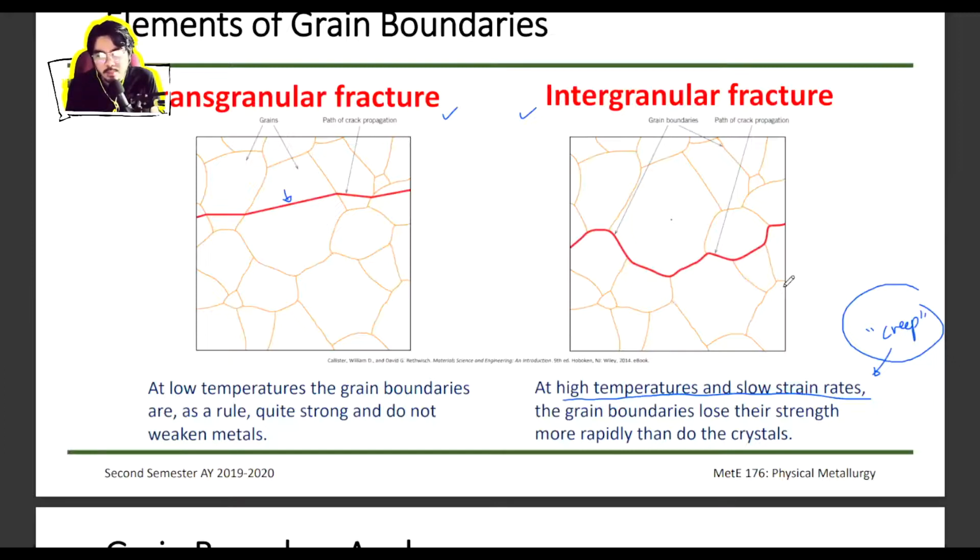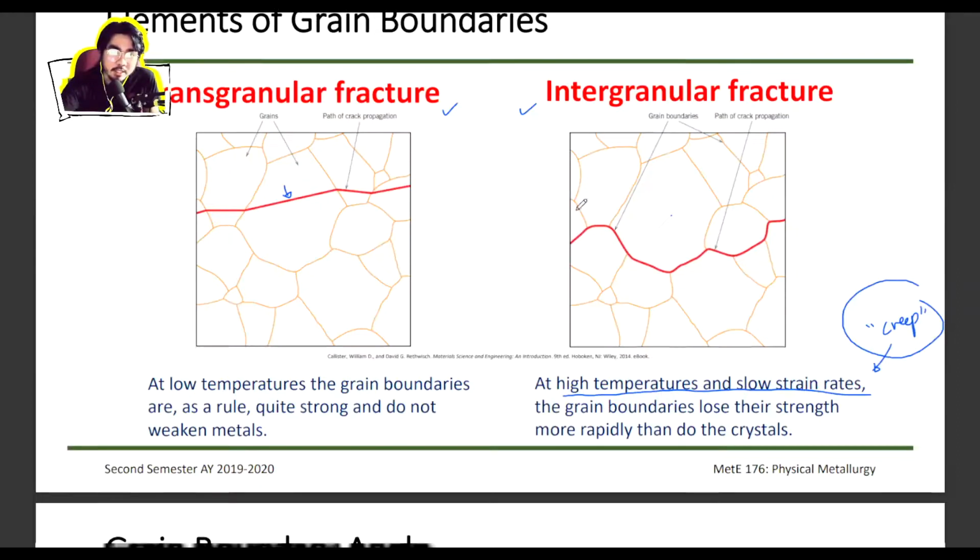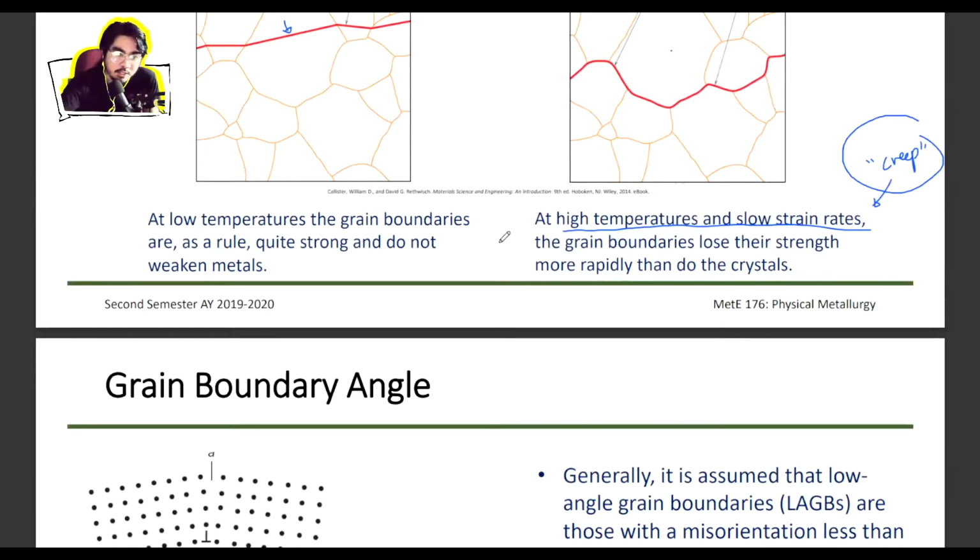So which is counterintuitive, no, kasi we always learn na smaller grains equals stronger material. So there are specific cases wherein larger grains will be more, ang tawag natin dyan is creep resistant, no? So if you know that your material will undergo creep based on its application, then it will be beneficial na i-adjust natin yung grain boundaries such that i-larger natin siya, no?